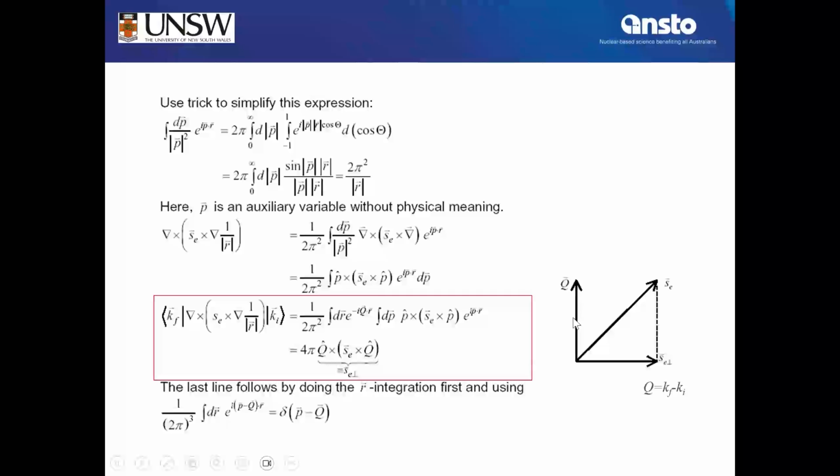So Q would be the momentum transfer by the neutron. That's the direction of the spins inside your crystal. And what we measure in the end is just the perpendicular component. That's what we need to know here. But that's perfect if you have a single crystal on a full circle neutron diffractometer.